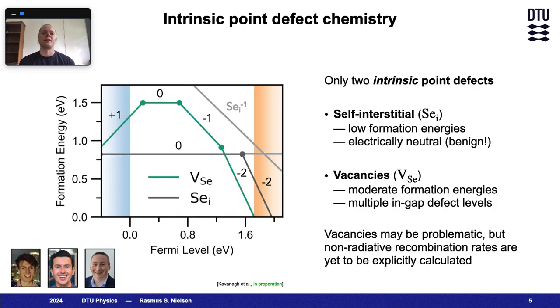Finally, it's a good idea to study the native defect chemistry to make sure that trigonal selenium is not intrinsically limited. Fortunately, when you're working with an elemental semiconductor, the number of point defects you need to calculate is only 2. The self-interstitials have the lowest formation energies, but fortunately, they're electrically benign and neutral across most of the bandgap. Vacancies, on the other hand, have moderate formation energies, so we'd expect low but non-negligible concentrations. And as the vacancies exhibit multiple charge transition states within the energy bandgap, these could potentially be problematic. However, we have yet to explicitly calculate the non-radiative recombination rates.